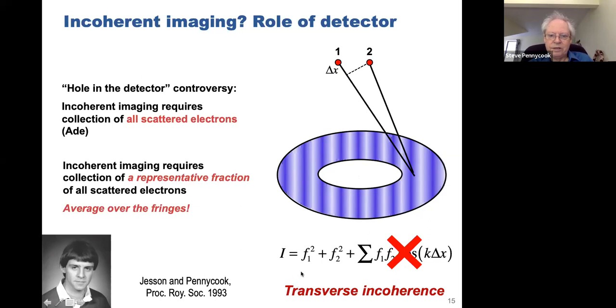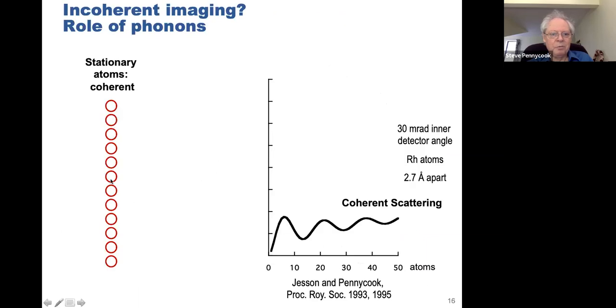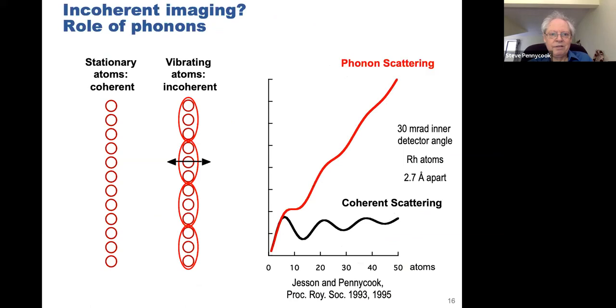That gives you incoherence in the plane of the detector, transverse incoherence. If you make a column of atoms and you calculate the scattering on the annular detector, you'll find that there is coherent interference between atoms at different heights. So this is the thickness dependence from coherent scattering, but actually atoms are not stationary. Let them vibrate. Thermal diffuse scattering, after all, they are vibrating. And so if you turn on phonon scattering, you get a little bit of residual coherent interference, but basically the signal then increases almost linearly with the number of atoms.